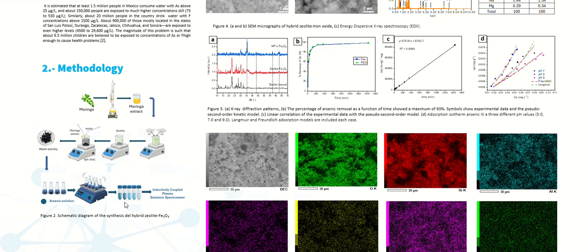For the kinetic study, 25 ml of arsenic solution were mixed with 5 grams of zeolite iron oxide. The suspension was continuously stirred at room temperature for 5 minutes, 10 minutes, 20 minutes, 40 minutes, 60 minutes, 2, 4, 6, and 24 hours. The liquid samples were subsequently filtered and analyzed by ICP.